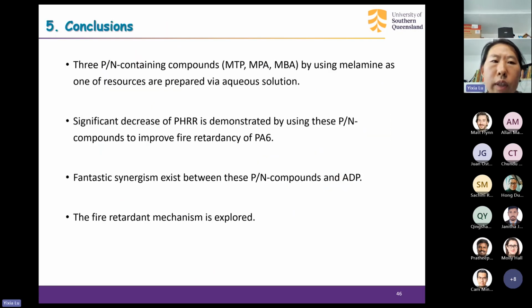So lastly, I'd like to give you a conclusion. Three PN containing compounds are synthesized by using melamine as the starting material, and we use aqueous solution in the reaction. We find a significant improvement by using these compounds and ADP to improve the fire retardancy of PA6, and it is found that a fantastic synergism exists between the compounds and ADP. And also in the research, we explored the fire retardant mechanism.